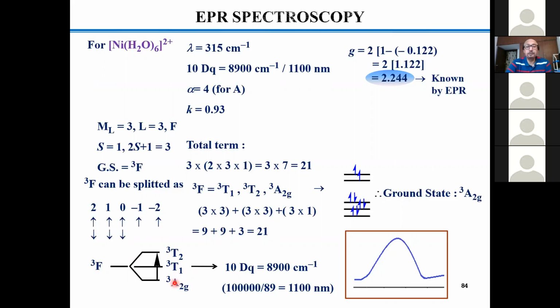Sir, so then it will be 3A, 3T1. And then the lowest energy would be 3A to 3T1. Okay, so that is your 10 DQ. That is a delta. Delta is the lowest absorption band from the d-d band I'm talking about, not the charge transfer band. And here you don't expect charge transfer because of the water. So from here to here, that comes around 1100 nanometer, which is almost 9,000 centimeter inverse. So 10 DQ is known.